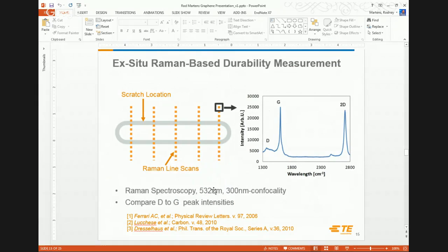Using the nanoindenter, we were able to do some wear testing of the graphene, and we went back to using Raman, so we would have a 20 micron wear track and then do Raman scans perpendicular to the wear track at different areas. And now we're going to look at a different portion of the peak, basically. So you see off to the right is the 2D peak, where we know that we have monolayer graphene. But then by examining the ratio of the D to the G peaks, we can determine how defective the graphene is. So the thought is, as we're wearing on it, we're going to start tearing it or introducing defects into the graphene film, so we can use that as a metric for its durability.